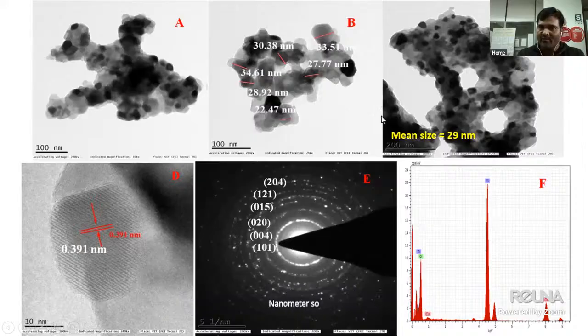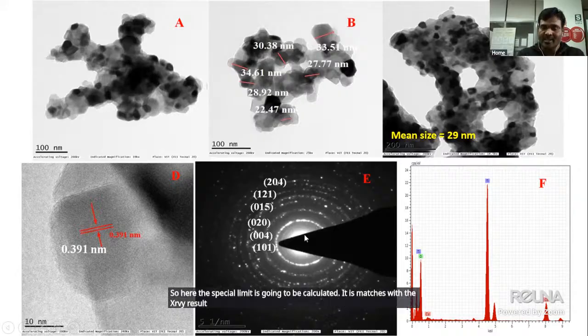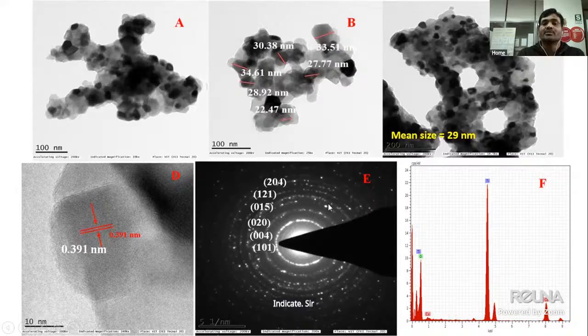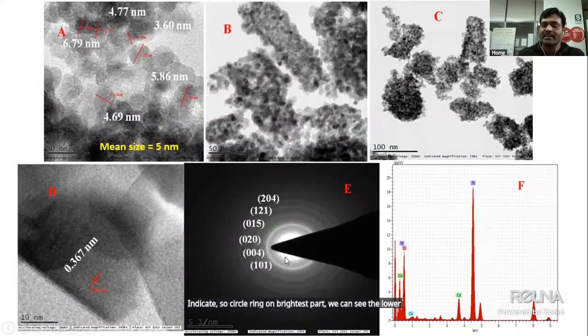So these are different magnifications of the TEM image of the titanium dioxide material. Here the d-spacing is going to be calculated. It matches with the XRD result. And here you see the SAED pattern is clear, indicating the circular ring with bright spots. We can see at the lower temperature there is only a circular ring, with no bright spots.